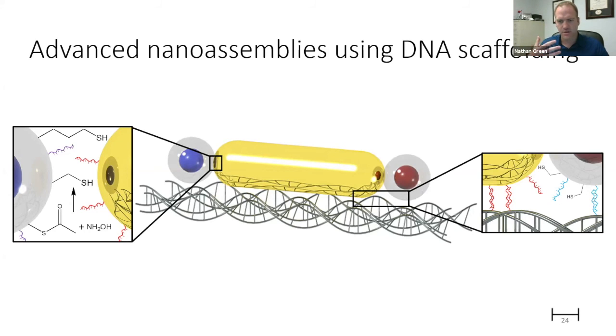I'm a chemist, and so I'm always thinking of different ways. DNA is really not my realm. I only recently got into this for my postdoc. And so I would like to build this initially not having DNA present at all. The idea of having DNA in there makes me nervous as a materials chemist because DNA is a horrible material. It falls apart way too easy. But it is good, I think, in the lab under controlled conditions, for getting these things lined up. Then we do that chemical modification to really lock these shapes in, and then we trash the DNA. All we need to do really is just heat them up a little bit, or we could pour in a little bit of salt, and the DNA would basically melt away from it.